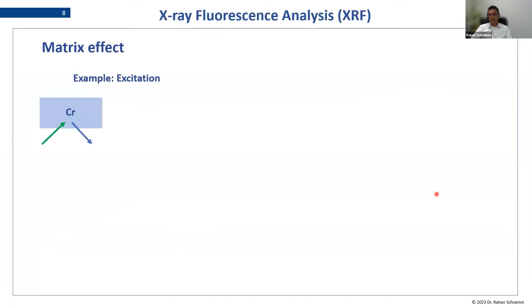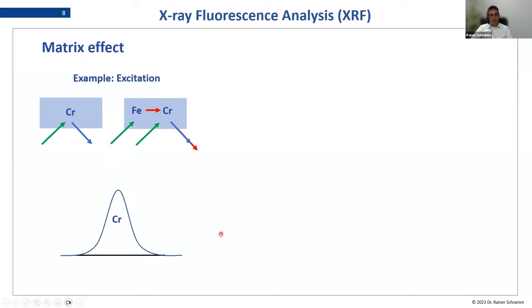And the first example would be excitation. So let us assume you have a sample with chromium as element, and the chromium will be excited by our X-ray tube, and this will create then chromium fluorescence radiation, which then will be registered by our detector. So this will result in a normal peak, like you see here. But now we have a second element in this sample, like iron. Iron is an element with higher atomic number, and it's so high that it's able to excite also chromium. That means the fluorescence iron radiation is not only sent out of the sample, it's also used partly to excite chromium. And this results in a higher chromium intensity than it would be without the iron.